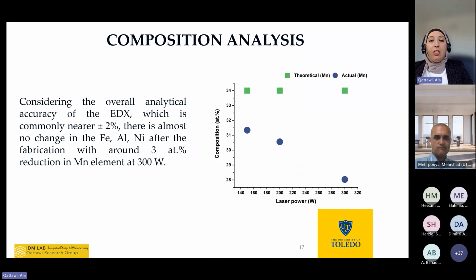And that's not unique to this system. It's actually a problem in laser powder bed fusion or laser-based additive manufacturing. And there are certain techniques we will want to explore of compensating for the loss of manganese. So eventually the green spots you can see here and the blue ones will not be very far apart, reducing the manganese loss and not losing a lot of the material's shape memory effect because of the loss of manganese.